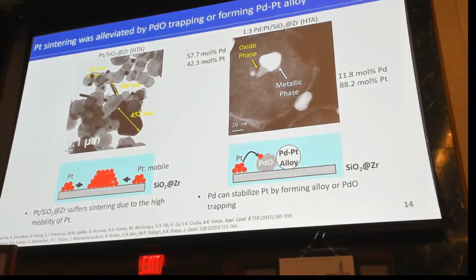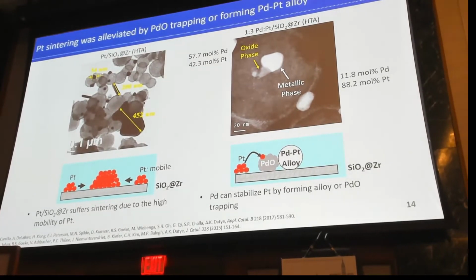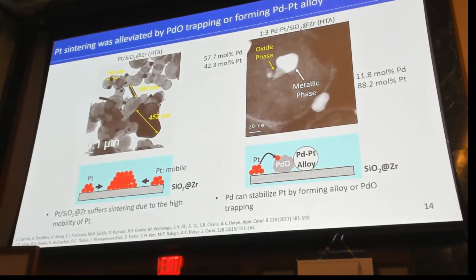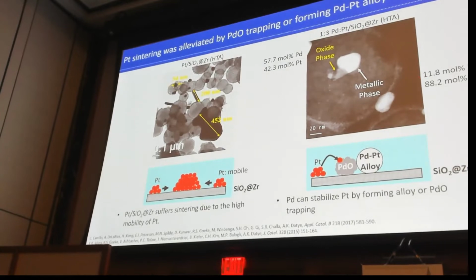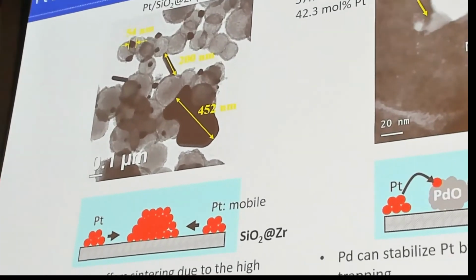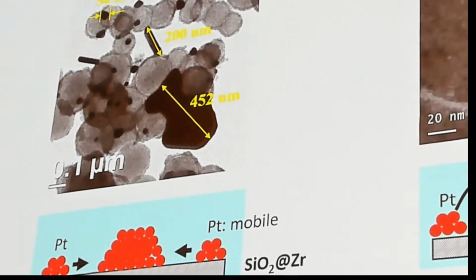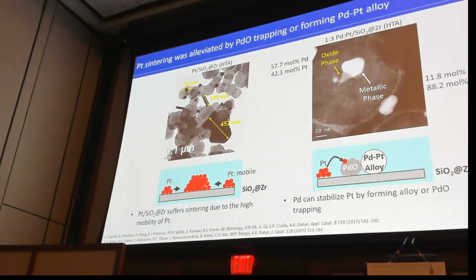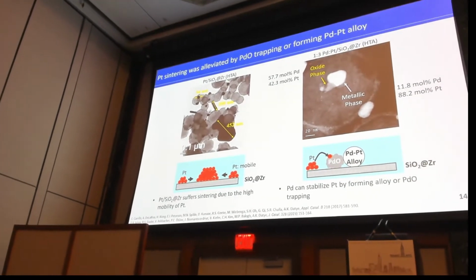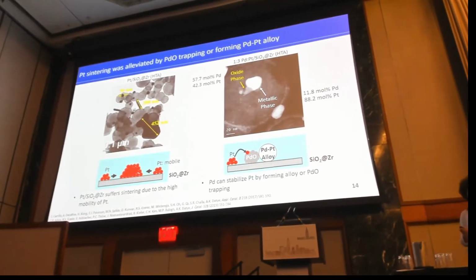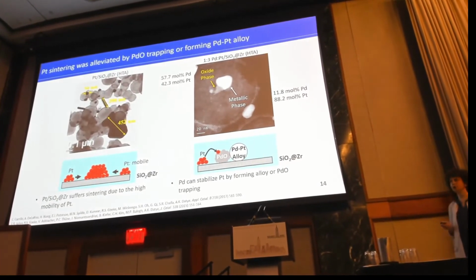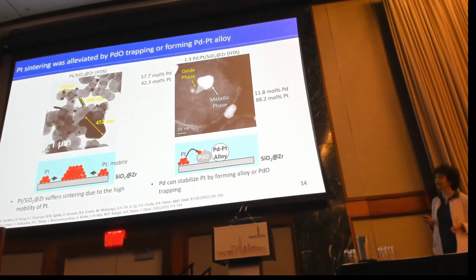So Professor Barker and his team did an EDS analysis of the metallic and the oxide phase. And what they found was, well, the metallic phase contained 12% palladium and 88% platinum, but more interestingly, they found that the oxide phase contained 58% palladium and 42% platinum. Okay, so that's interesting information because up to that point, we always thought that the oxide phase is PdO, right? But now we can see that the oxide phase contains both palladium and platinum.